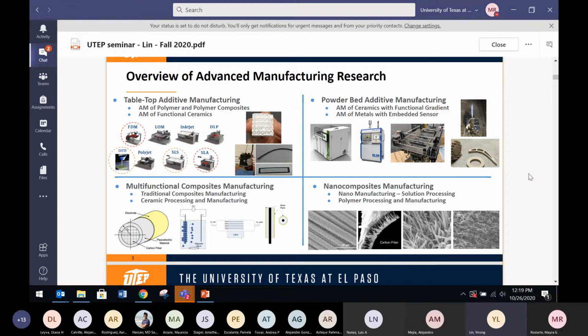Lastly, to the lower right is what we're working on in the nanocomposites side. We do a lot of material synthesis, like I said, right? This picture, second from the left, is a carbon fiber with zinc oxide nanowires on it. We use a hydrothermal process to grow nanowires on these carbon fibers. Not only does it increase its mechanical properties, but at the same time, it brings integrated embedded sensing or embedded damping into them.